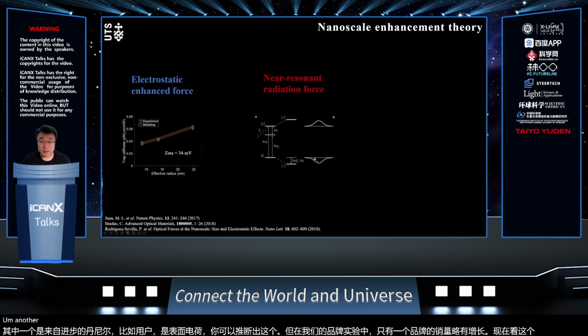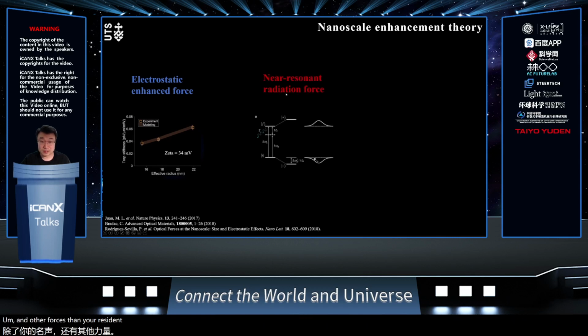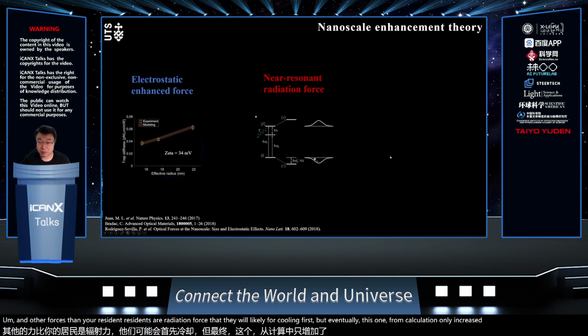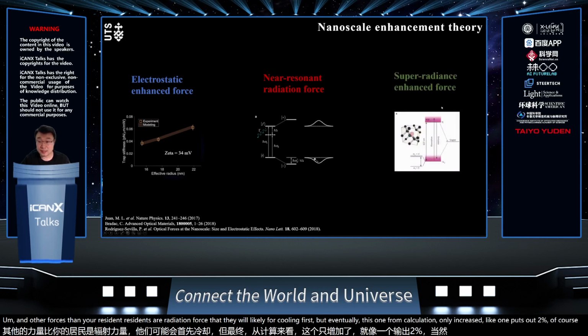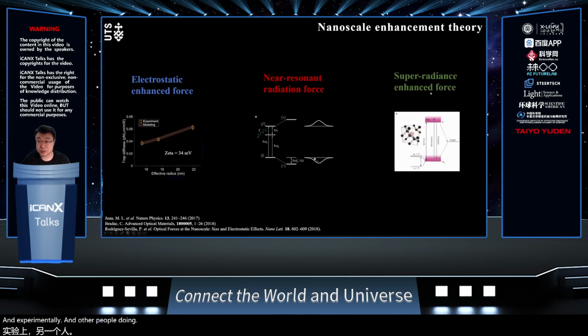Another force is the near resonance radiation force, a little bit like the laser cooling force, but from calculation it only increased the force by like 1% or 2%. And experimentally, other people used superradiance, and by using this, basically all the defects in the NV center work like one big dipole. It does have enhancement, but only 20%. So the enhancement is really limited.